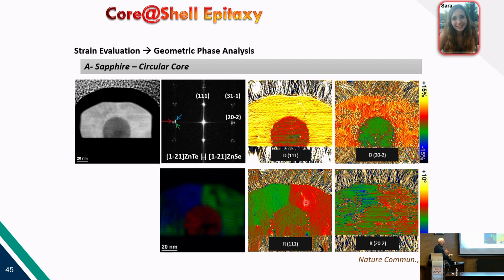So this is a kind of elastic relaxation, but also you see a lot of misfit dislocations on the side, which is a kind of plastic relaxation. So there is a combination mechanism between plastic and elastic relaxation that at the end makes the material grow perfectly, let's say, epitaxial, but relaxed. So the material creates defects, and it's flexing, but let's say the cell parameter is exactly the same in the whole shell. So the material is not strained, it's relaxed, but it has to somehow deform.